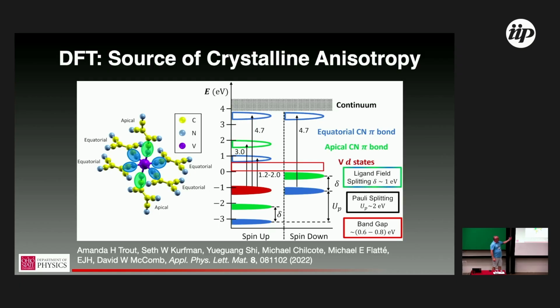What I suspect we were seeing in the nanowire case, where we identified a unique strain axis, as well as in the thin film case for temperature and with the piezo, is that as it grows, we have at least sort of nematic order, that the different grains probably tend to orient with these planes of equatorial CN all lying in the same direction. And that's what gives rise to this orange arrow on the previous plot.